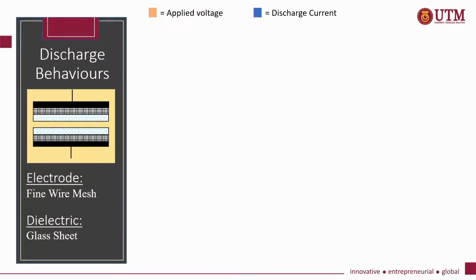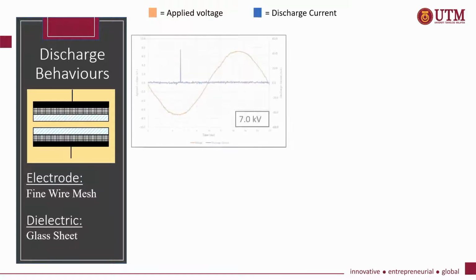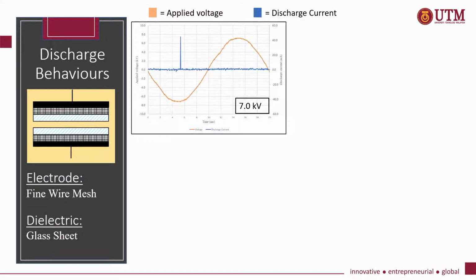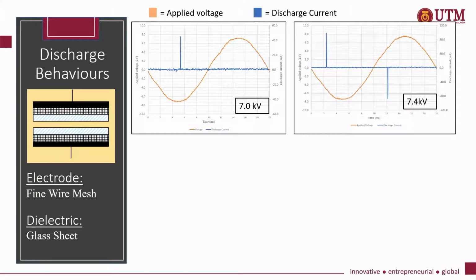So this is the example of the configuration with fine wire mesh as electrode and glass sheet as dielectric. As we can see, at 7 kV, the gas starts to break down, and one half cycle consists of a single pulse current discharge. And when the voltage is further increased to 7.4 kV, the glow discharge was generated, and it is indicated by a single pulse discharge current in both of the half cycles.